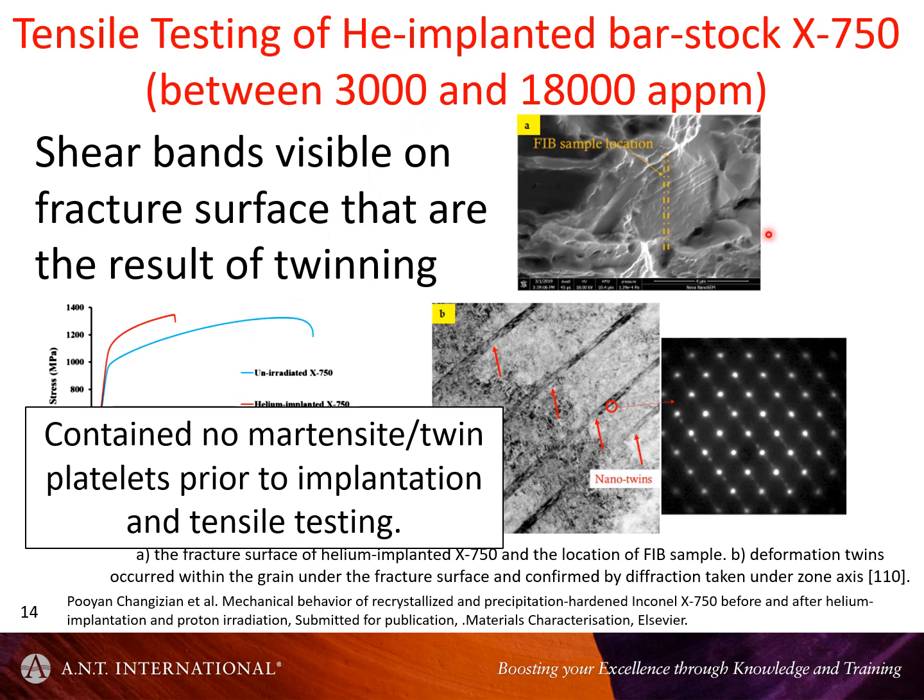And basically, it's a representation of what one can expect in Inconel spacers in the CANDU reactor at a fairly low dose, something like up to 10 dpa, for example. So this is what we expect, and this is the corresponding increase in the strength, and we haven't got to the point where it decreases again with higher helium concentrations yet.